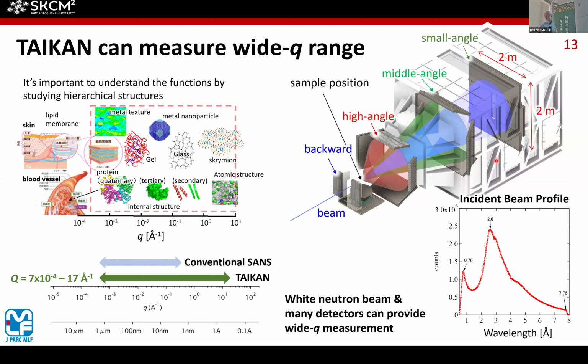How does TAIKAN do this? We use the white neutron beam. It means the wavelength of the neutron is from 0.8 angstrom to 8 angstrom. This white beam comes from the target to the sample, then it's scattered. Then we measure the scattered neutrons using wide-angle bank detectors, so it means a wide two-theta. The combination of the white beam and these many detector banks can provide wide Q measurement.